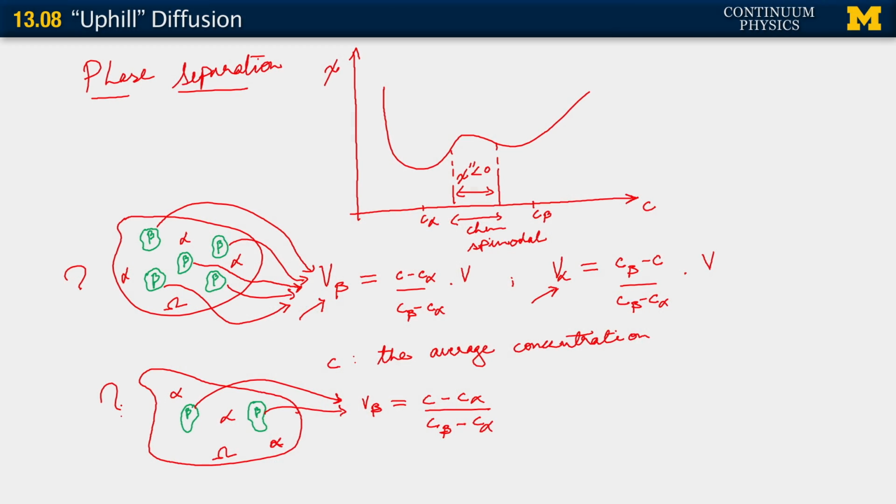If you have a background in material science, or you've considered related problems, you may have an idea. So think about it. There is something about these two pictures, which I've just drawn, which the formulation does not address at all. It does address the total volume of beta and the total volume of alpha. But it does not address something else which controls the way in which beta and alpha distribute themselves into certain numbers of particles. What it doesn't tell us is how big those boundaries between alpha and beta are.